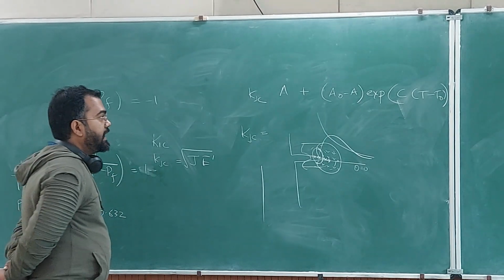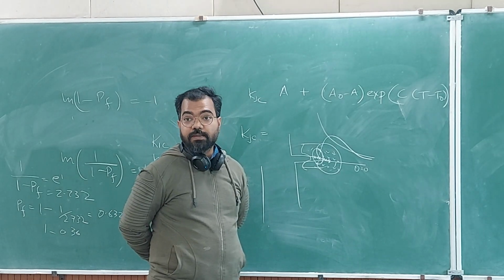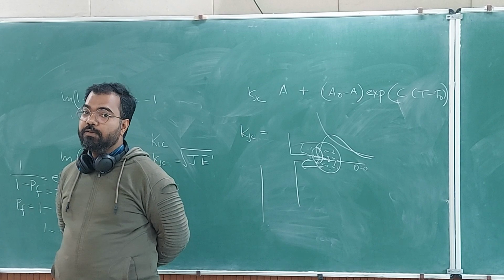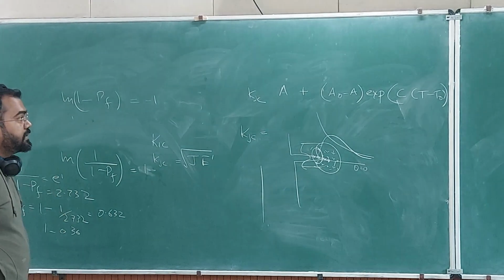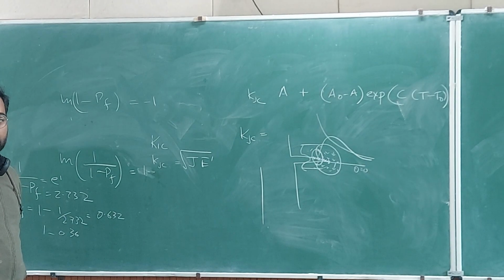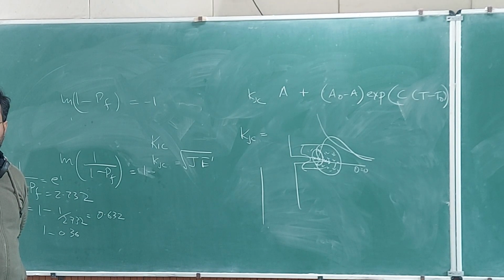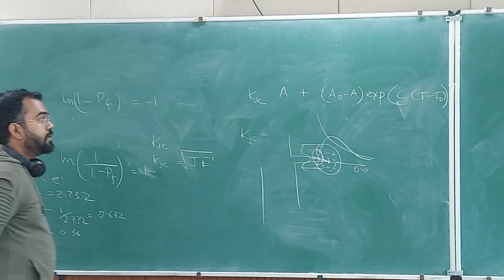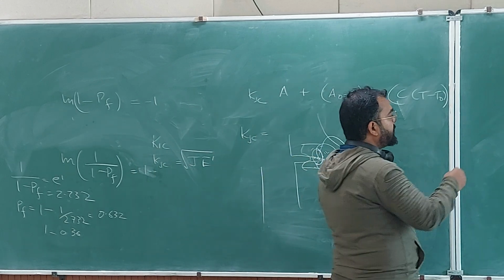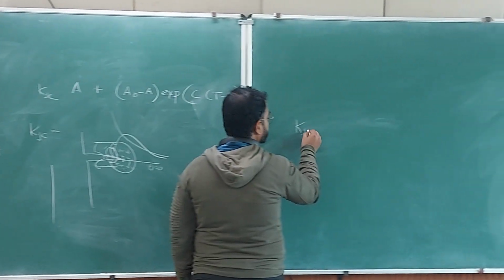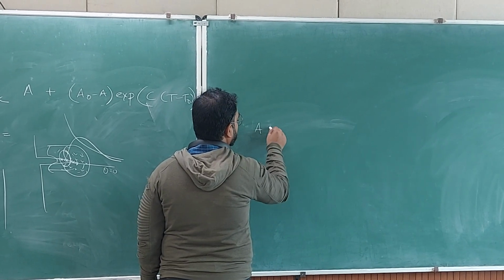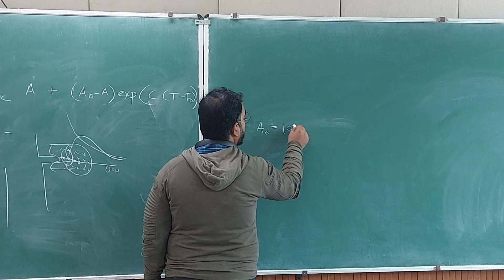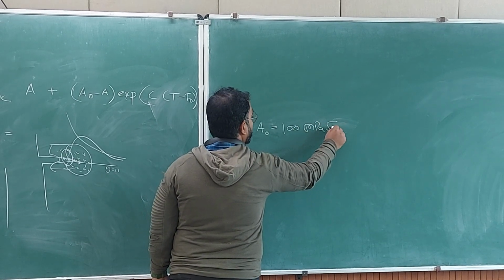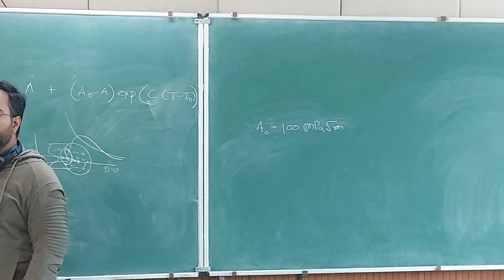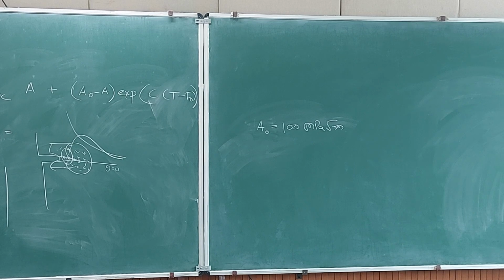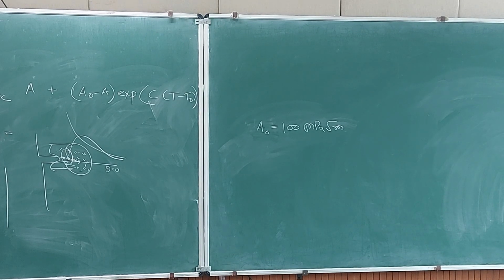Okay, and C is a constant. A naught is the reference value of fracture toughness, so you have to keep some value of A naught. T is the temperature, and T naught is the temperature where this value will be attained. Okay, so with a lot of experimental work and discussion, the KJC value, or A naught value, comes out to be 100 MPa root meter. So we are interested in a temperature where KJC attains 100 MPa root meter.